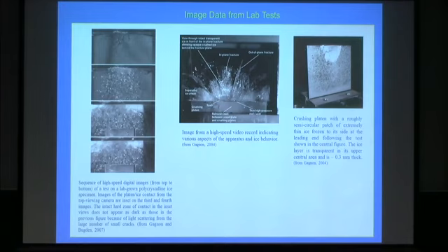It's inset at the same scale as these images, so that the pressure is indicated by the width of the contact here on the pressure sensor. So that corresponds to this hard zone region up here, and same sort of thing down here. High pressure here, lower pressures on the sides. We've already seen this. I think I mentioned that we were able to get a liquid or slurry layer thickness measurement from here that matches pretty well with the other one that I mentioned.